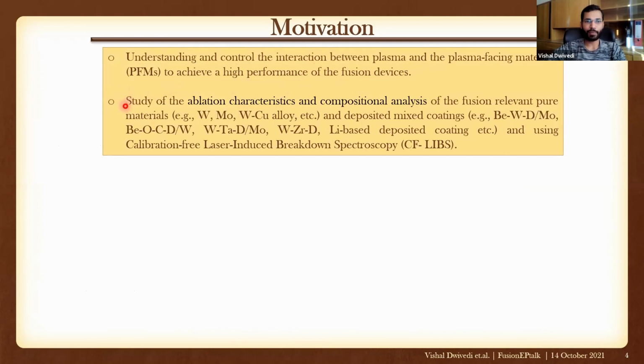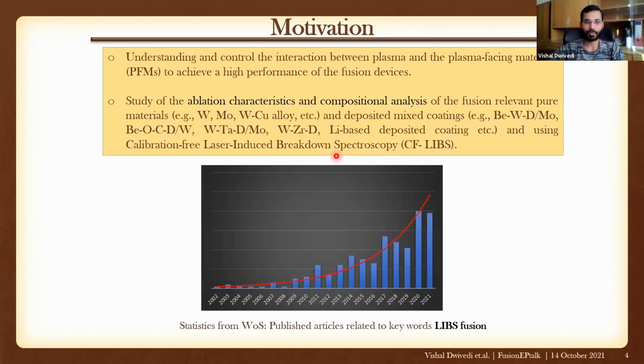So in this work, I will present the study of ablation characteristics and compositional analysis of the fusion-relevant pure materials, which are tungsten, molybdenum, tungsten-copper alloy, and also some deposited mixed coatings: beryllium-tungsten-deuterium, beryllium-oxygen-carbon-deuterium, tungsten-tantalum-deuterium, tungsten-zirconium, and lithium-based deposited coatings, using calibration-free laser-induced breakdown spectroscopy.